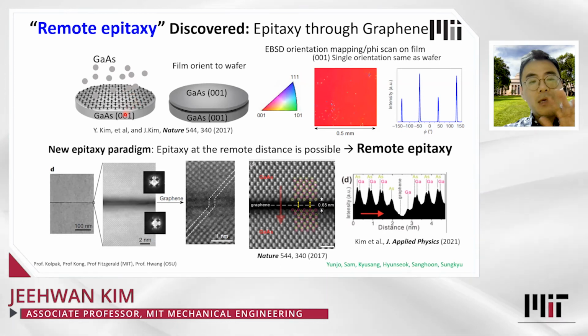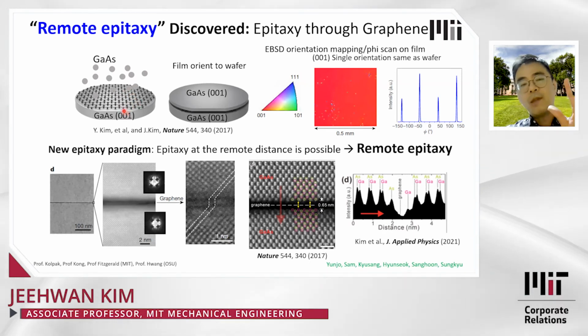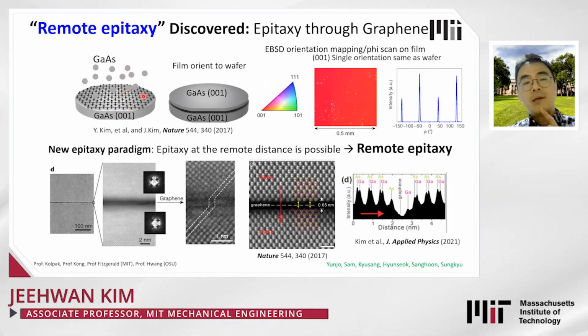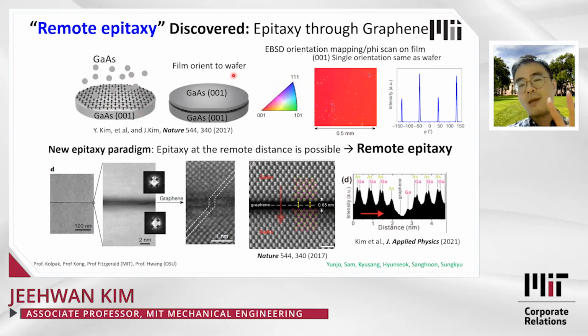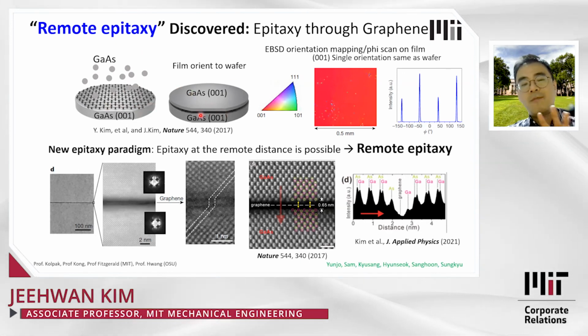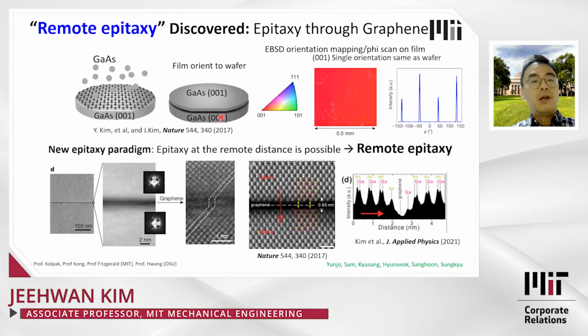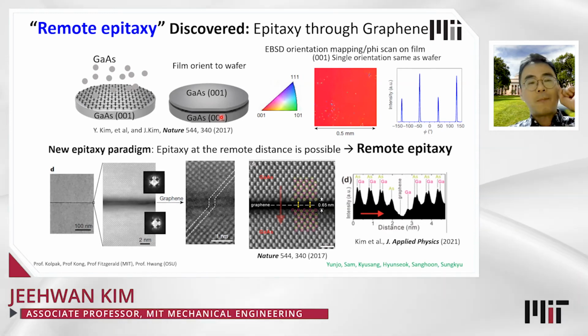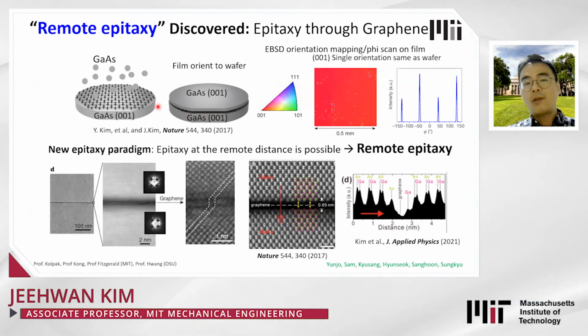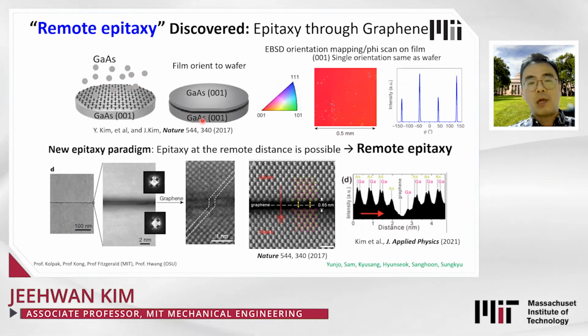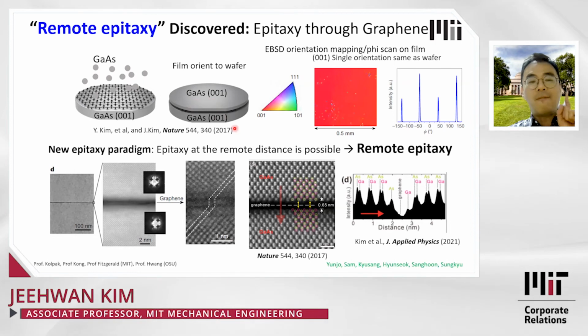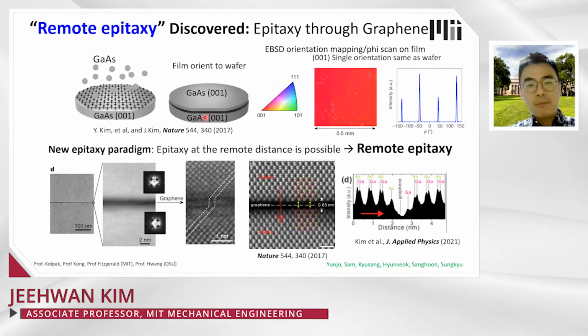This ionic bonding field can penetrate through the graphene, and this strength can be stronger than the van der Waals interaction of the carbon. If that is the case, whatever you grow on the graphene on the wafer, this material will follow the crystalline information of the underlying substrate, even if there's graphene. That is what we have found. We verified this hypothesis by growing gallium arsenide on graphene on gallium arsenide. By doing so, we are able to grow perfect single crystalline gallium arsenide following the underlying substrate, even if there's graphene.